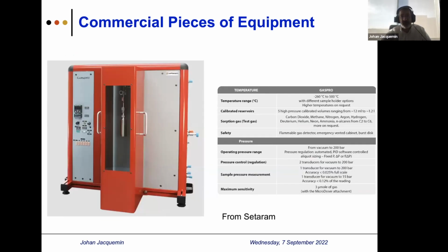And just a brief note on Setaram equipment. It's again turnkey equipment, and if you do not have any experience, you may directly have the concentration of gas expressed in different ways. But I received such a piece of equipment that I'm currently testing, in a fully manual mode, because you have to be aware that with such a technique, we have a heater which heats only the sample reservoir and not the full cell, and you need to calculate the temperature gradient which occurs over the full cell, even if you have a thermocouple to guide you. Anyway, you must take that into account.